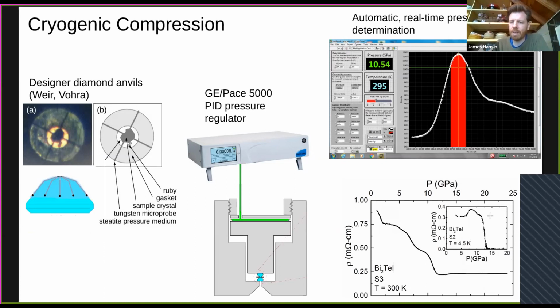So it turns out that this transition is connected with a structural transition that still occurs even during low temperature compression. And so this is a useful tool, one, because it allows you to very rapidly screen something for pressure-induced superconductivity, but two, because it can lead to different phases during low temperature compression. And I'll talk about that for a moment.